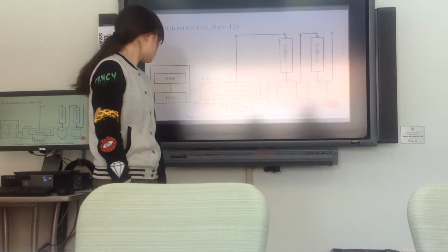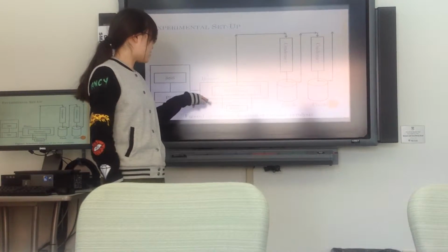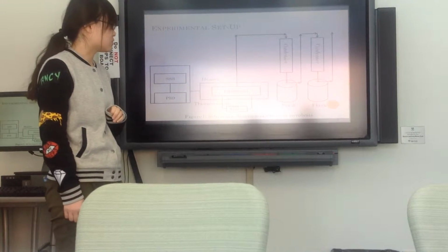This is the experimental setup. First, I have a PID to control the temperature, and the SSR to provide the power, a cylinder heater and stainless steel used as a pyrolyzer, a thermocouple to measure the temperature of biochar, and two water-cooled condensers and two ice-cooled flasks to collect the bio-oil.